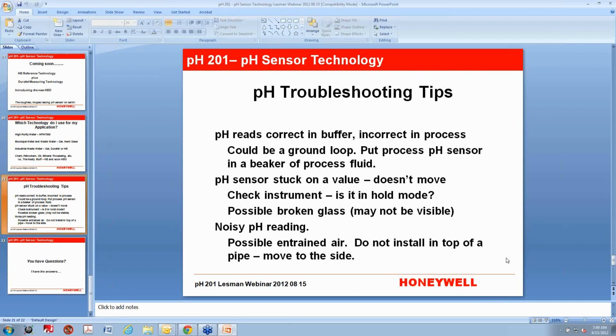The symptom from broken glass is this: when the glass breaks, you get a dead short between the measuring electrode and the reference electrode. And so then it just sticks on a number. A lot of people say, oh, if it sticks on 7, it's broken glass. But that's not necessarily true. I've seen them stick on all kinds of weird numbers. It doesn't really matter, because once the glass is broken, the internals start getting flooded with process fluid, and that changes all the voltage properties in the sensor. So it won't necessarily be stuck on 7. It could be stuck on anything.